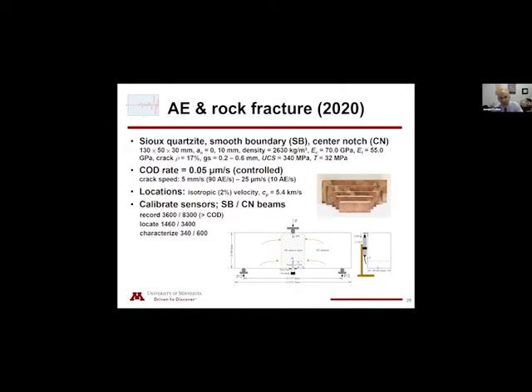And it's slow. It is 5 millimeters per second. I'll show you some results where, again, the crack speed is, for us, quite rapid. We were able to control the rate of AE was quite high for us, 90 events per second. And then the crack slows down, this 25 microns per second approximately, with a rate of AE of about 10. This material, this rock, is fairly isotropic for P wave velocity within 2%. This is the P wave.